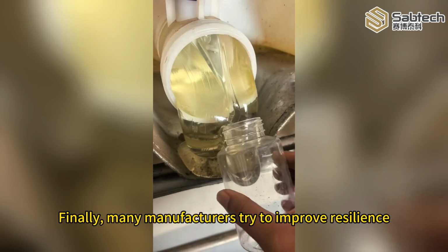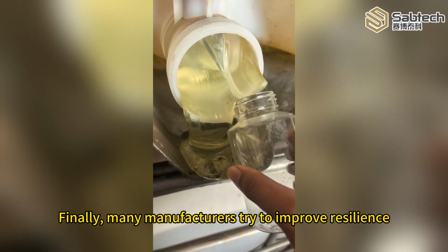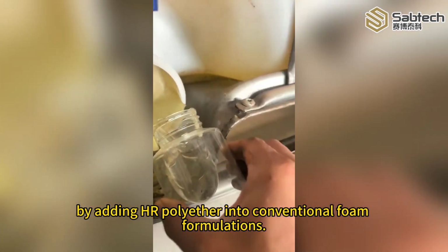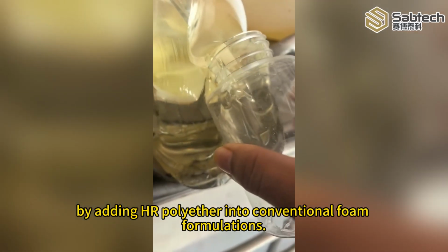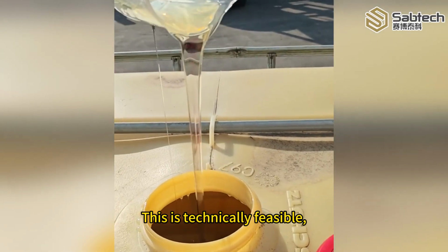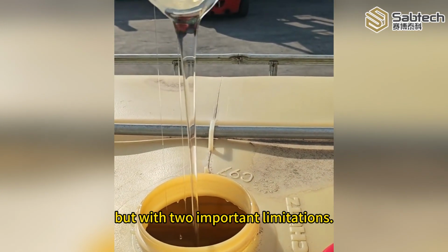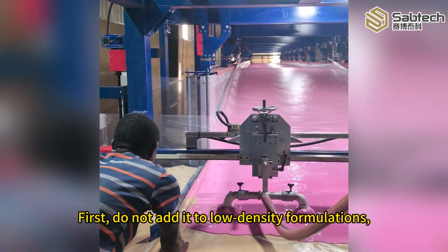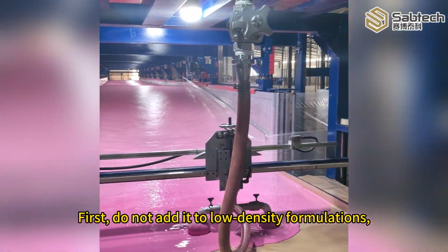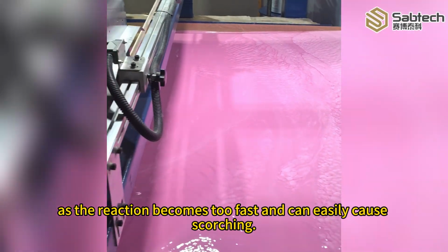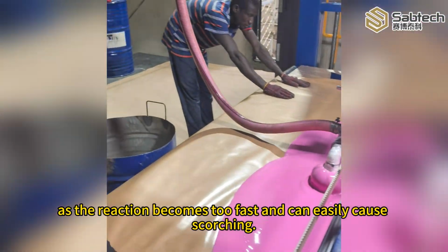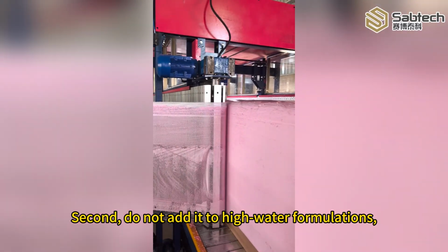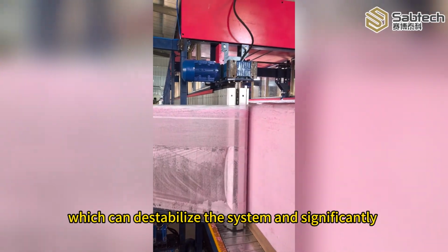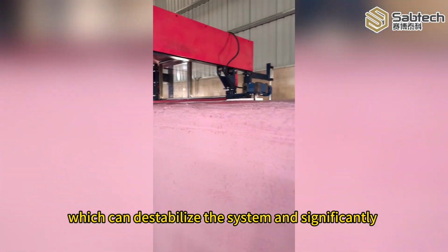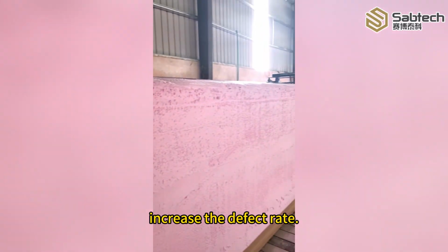Finally, many manufacturers try to improve resilience by adding HR polyether into conventional foam formulations. This is technically feasible, but with two important limitations. First, do not add it to low-density formulations, as the reaction becomes too fast and can easily cause scorching. Second, do not add it to high-water formulations, which can destabilize the system and significantly increase the defect rate.